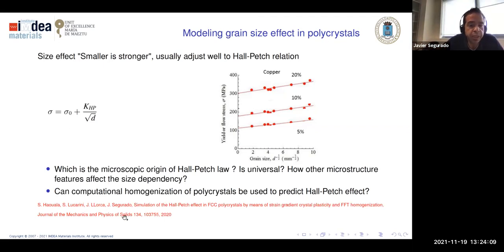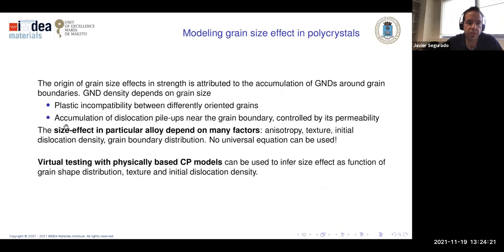So what I'm showing here is this work that we published in JMPS, where we try to apply crystal plasticity in FFT homogenization, some special kind of crystal plasticity, to answer some of these questions. What is the physical origin of the size effect? It is more or less well accepted that it is the accumulation of geometrically necessary dislocations around grain boundaries.